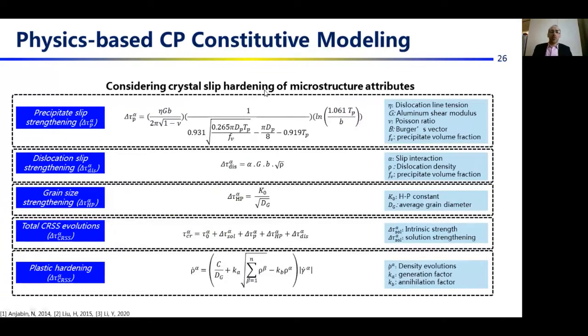Physics-based CP modeling includes the slip strengthening effect of precipitate phases, dislocation density, and grain size, and it considers the total critical resolved shear stress, which is the total slip strength, as the summation of each of these independent effects. And finally, the plastic hardening, which is the variations in the dislocation density during the plastic deformation.